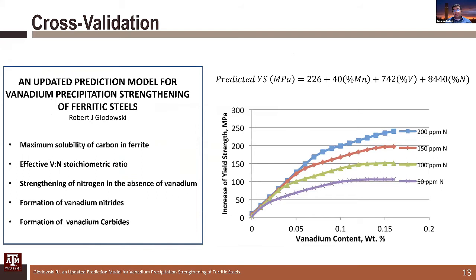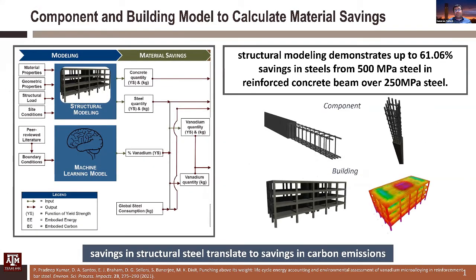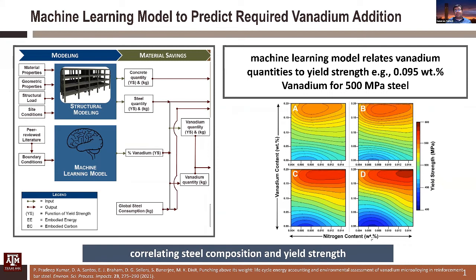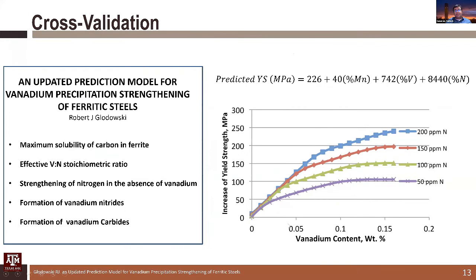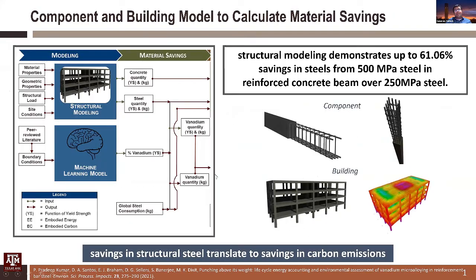And we actually come up with numbers that are pretty close to some numbers that Vanitec has reported previously. So this is from data from Dr. Glodowski, who is a consultant with Vanitec, at different nitrogen concentrations. So we come up with a pretty good agreement with these numbers. So once we have a functional unit correlating vanadium composition and other concentrations to the steel tensile and yield strength, we can then do structural modeling, both at the level of single structures as well as entire building level structures.